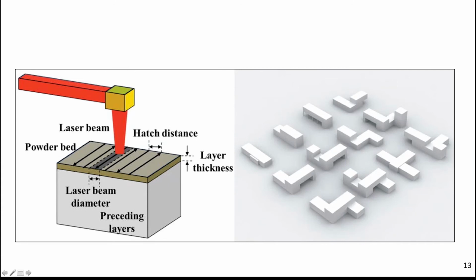And what is remarkable is that just by controlling and changing slightly this hatch distance, layer thickness, but also the power of the laser and the scan speed, I can achieve very, very different properties. So I don't need to change the material. I can play with a single material and change its properties quite significantly. And this is what I call modular design. So I can, like Lego, have different bits and pieces that I assemble together. And by changing the parameters on the left-hand side, I can assemble something with different properties.